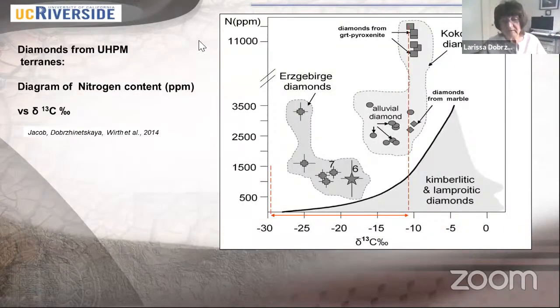So now we would like to see again how these parameters, nitrogen content versus delta 13, are compatible with kimberlitic and lamproitic diamond. We have the same diagram of Cartini plotted with our data. This is diamonds from Kokchetav Massif, diamonds from Erzgebirge Massif. This is kimberlitic diamond. We see that they belong to different fields. So the ratio of nitrogen to delta 13 is definitely different.